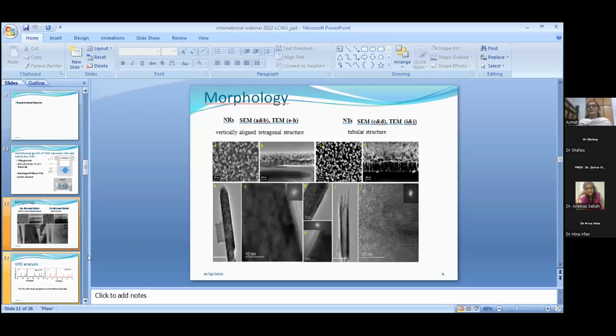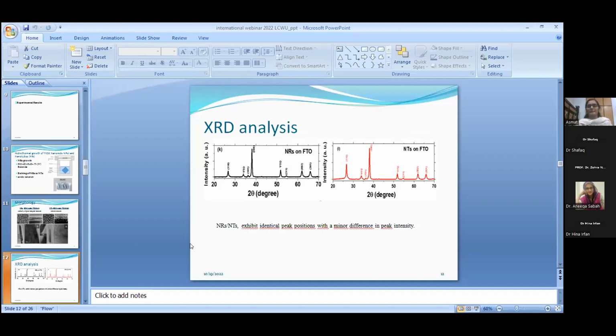Now moving towards the XRD analysis. These are the XRD analyses of the nanorods and nanotubes. We have diffraction peaks at the 101, 002, and 211 planes, which show the rutile phase of titanium. And the higher intensity at the 002 plane rather than the 101 plane shows that the rutile titanium nanorods are aligned in the 001 direction, that is, grown perpendicularly to the FTO. And we can see from this figure that the nanorods and nanotubes exhibited identical peak positions, but a minor difference in intensity. That shows that the etching does not affect the rutile phase of the nanotubes.